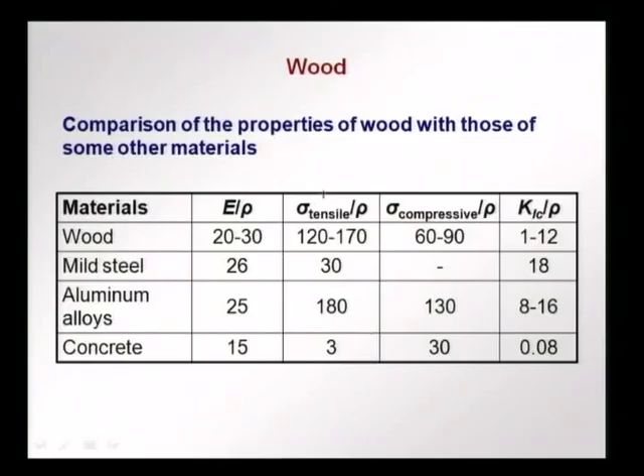In terms of the tensile strength, again divided by the density or relative to the density, we have wood having values of 120 to 170, much better than mild steel and comparable to aluminum alloys, and much better than concrete, which is very weak in tension and also has a high density. In terms of the compressive strength, again wood has good values, 60 to 90, which is comparable to aluminum and much better than concrete. Fracture toughness K1C divided by rho, the density, again in wood you have a wide range from 1 to 12, which is comparable to the metals and much better than concrete, which is a brittle material and a heavier material.